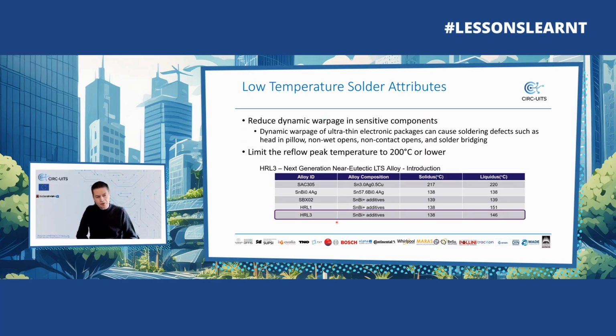The downside of using tin bismuth alloys is bismuth is notoriously brittle. So that meant if you solder a BGA package on a PCB and you do a drop shock test, the BGA will just drop off, and that hindered the introduction of low temp solder in various types of industries.